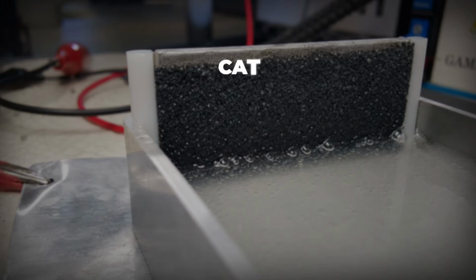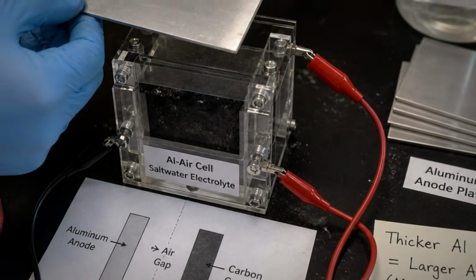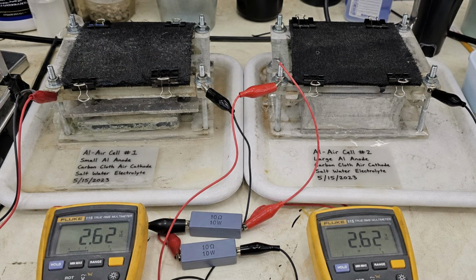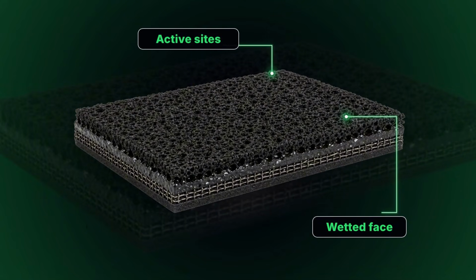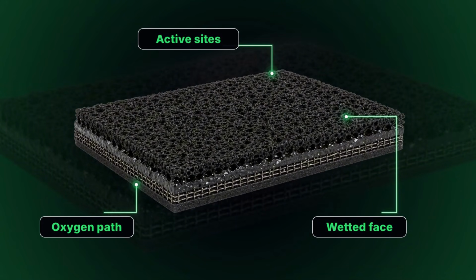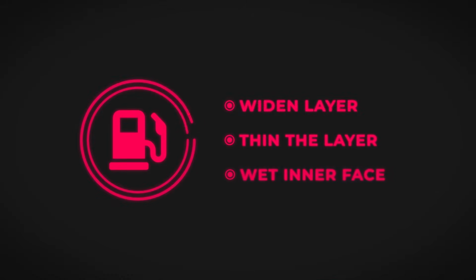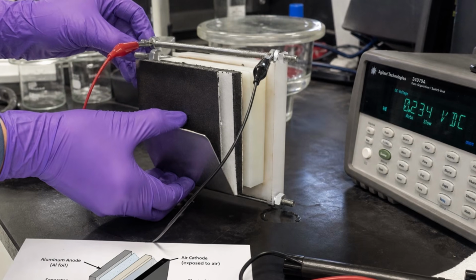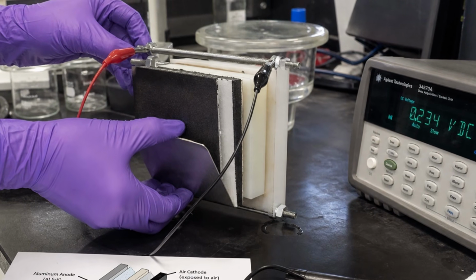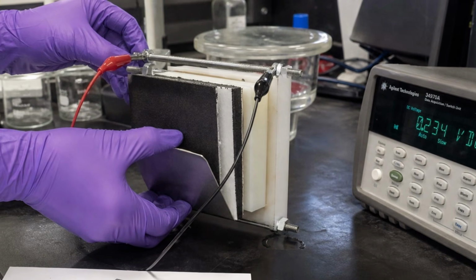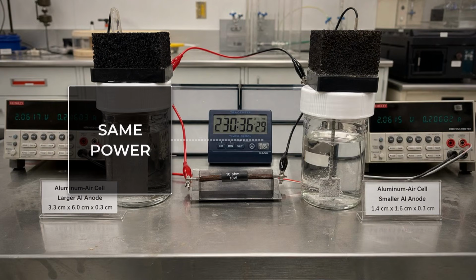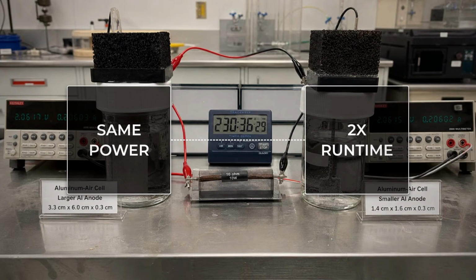The second is that your bottleneck is the cathode, not the fuel. Almost everybody building one of these instinctively adds more aluminum, and it changes very little. Output is limited by how quickly oxygen can reach the reaction sites in the carbon layer. Widen that layer, make it thinner, make sure it is properly wetted on the inside face while staying open to air on the outside, and the current climbs. Double the aluminum, and you have doubled your runtime without touching your power.